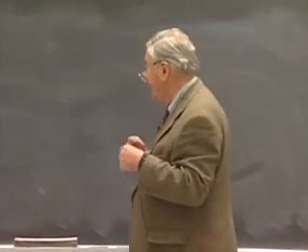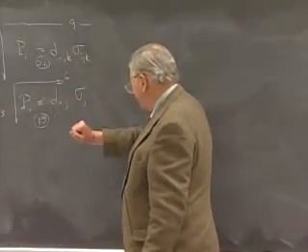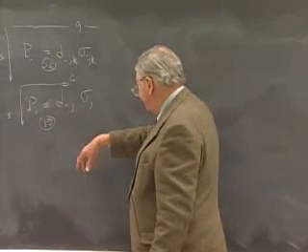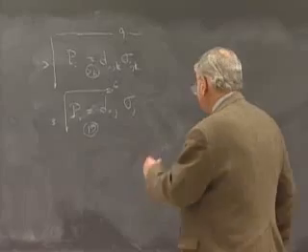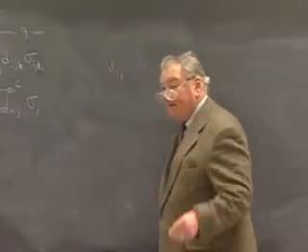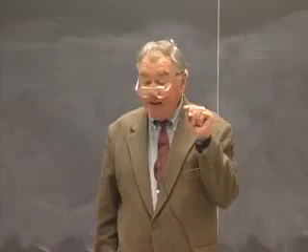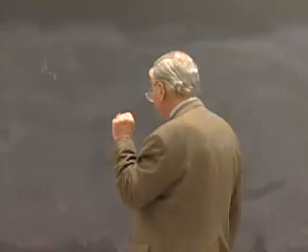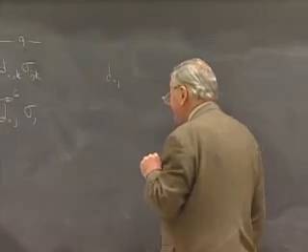So what you have to do in any generic problem of this sort is, for a particular single crystal, look up the form of the dij matrix that will have the equalities between tensor elements written in, and the zeros, those moduli which are identically 0, entered into the array.